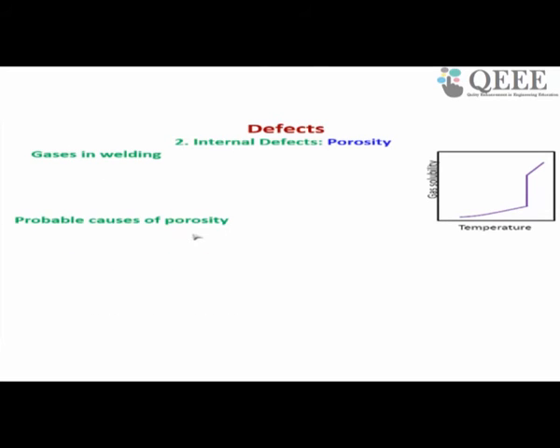Next is porosity. Porosity is also a type of internal defect. What is porosity? We do welding in atmospheric conditions. In the atmosphere we have different gases like nitrogen, hydrogen, oxygen and others. These gases have very high liquid solubility and very low solid solubility. You can see from this diagram, at high temperature the solubility limit is very high. However, at low temperature the solubility limit is very low.